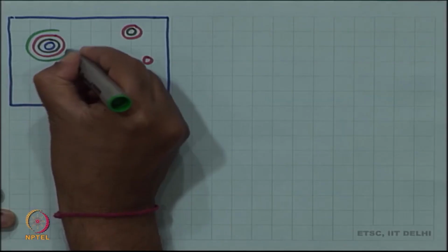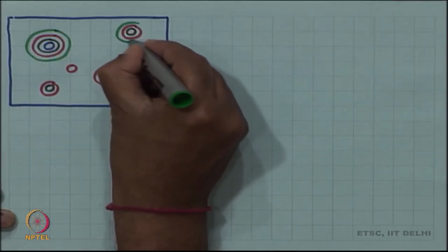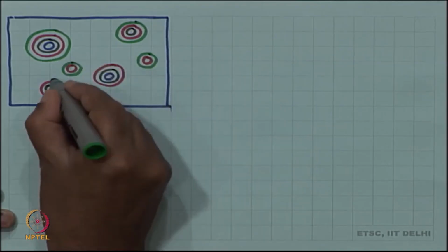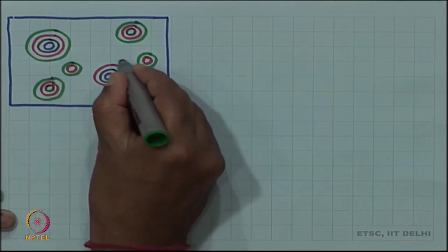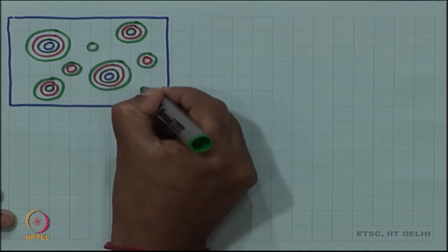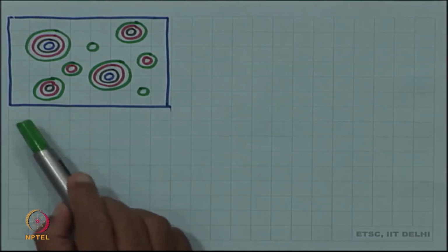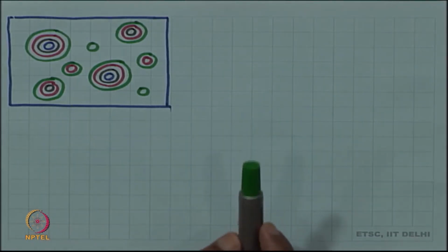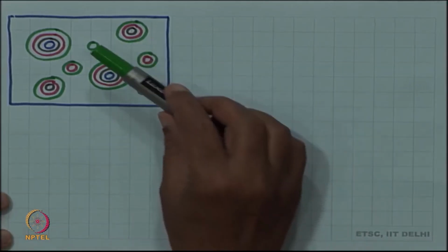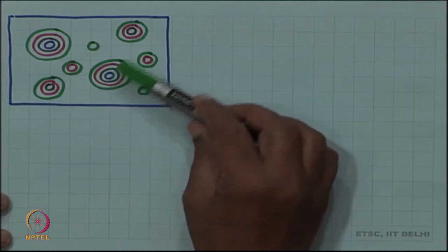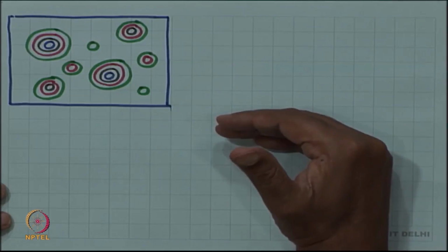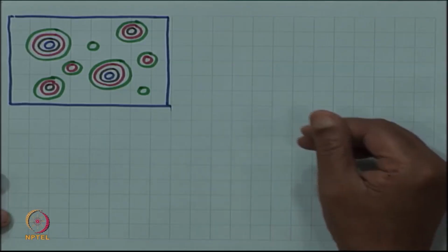So, in still next event, all these existing particles which are growing will keep growing and still new nuclei will form. So, one can see that gradually with this process of nucleation and growth, new nuclei are forming and already existing particles are growing. So, the overall transformation rate will depend upon both the nucleation rate and the growth rate.